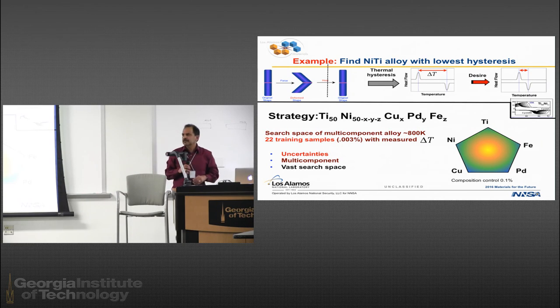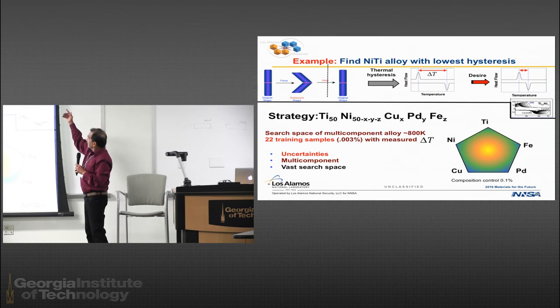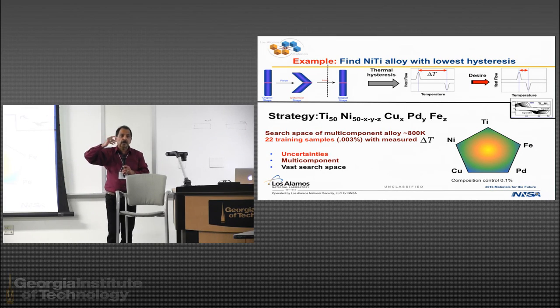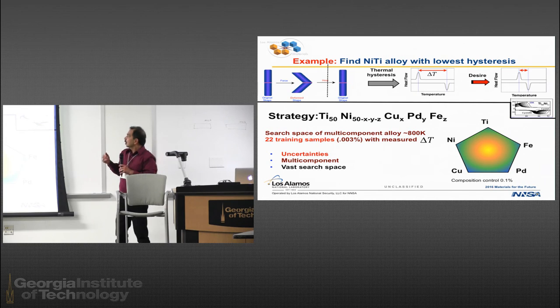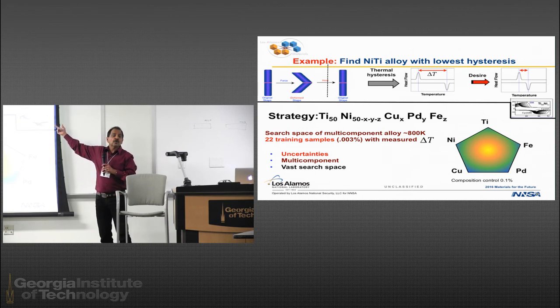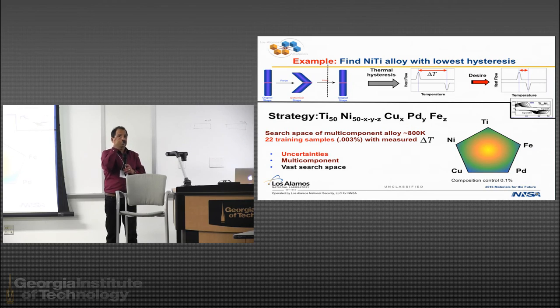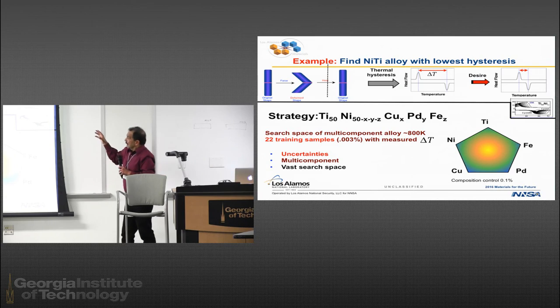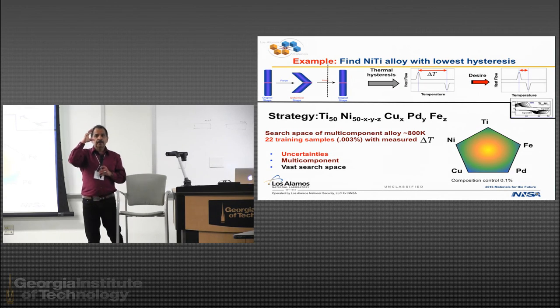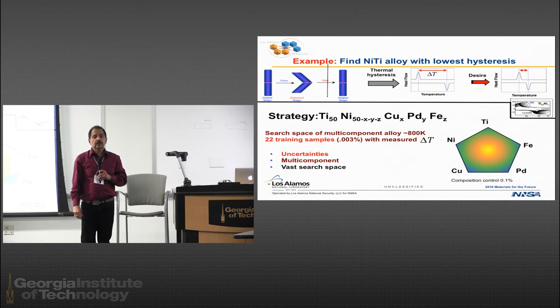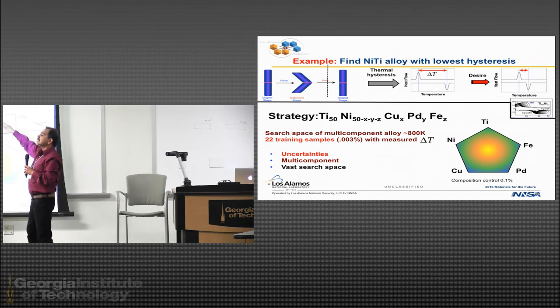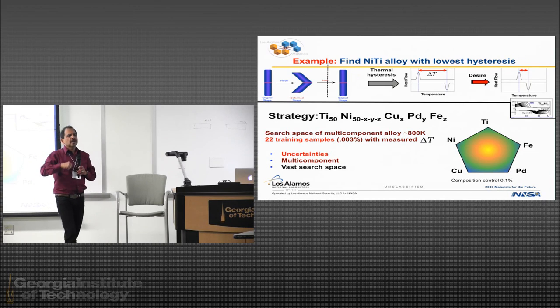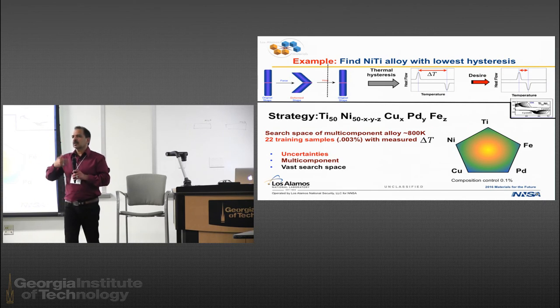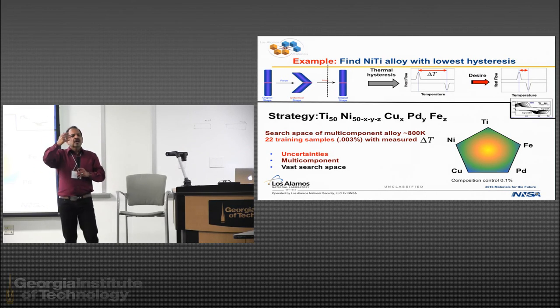How are you going to do this? So here, for example, is nickel titanium, okay, which is used in industry a lot. And you can see that the spread is of the order of 25K with cycles. And also the interval, this delta T, is also of the order of 25-30K. So our strategy was, okay, we're looking for a multi-component alloy with very, very small thermal hysteresis. And so our domain knowledge told us that we're going to restrict ourselves to this family. We have a good idea as to what copper does, what palladium does, and what iron does in terms of how it affects the transition temperature, et cetera.